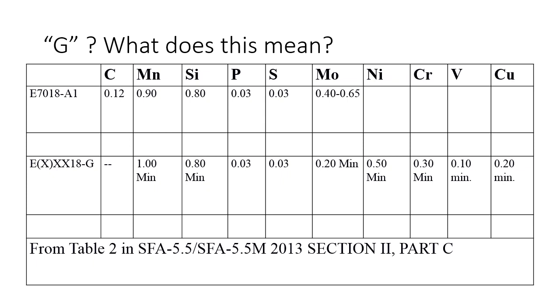So this is from Table 2 in SFA 5.5 or 5.5M 2013, Section 2, Part C. This is from ASME. You can see that we've got the chemical composition, the chemistry for an E7018-A1. So our carbon content would be 0.12. We'd need a 0.9 for manganese. Silicon, phosphorus, and sulfur, those would be our maxes. And then our molybdenum would be between 0.4 and 0.65.